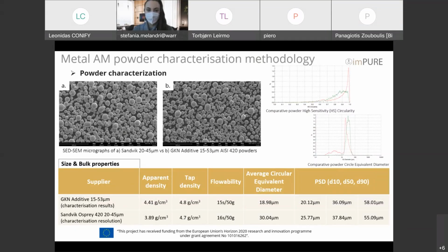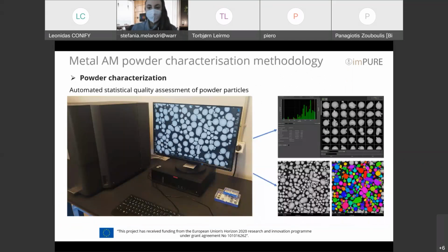Here are some characteristic results from 2 different powders. In this case, Sandvik and GKN Additive were the suppliers of AISI 420 powder. You can see SEM micrographs of both powders, and some of the characteristics of the morphology and the shape, such as the high sensitivity, circularity, and the circle equivalent diameter. And of course, as mentioned earlier, results on apparent and tap density, on the flowability, and the particle size distribution with D10, D50, and D90 values shown in the table. Next slide, please, Stefania.